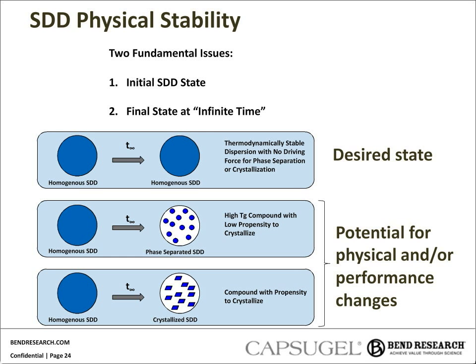The place where we generally live in the spray dry dispersion world is a place where we depend on kinetic stability. In those cases, we start from a homogeneous SDD, and over an infinite amount of time, it will eventually phase separate, either into amorphous systems or crystalline. As I'll get into on the coming slides, it's important to note that we are in a kinetically stabilized regime, which allows us to do some things in terms of accelerated storage and predictive modeling around the stability of those systems.